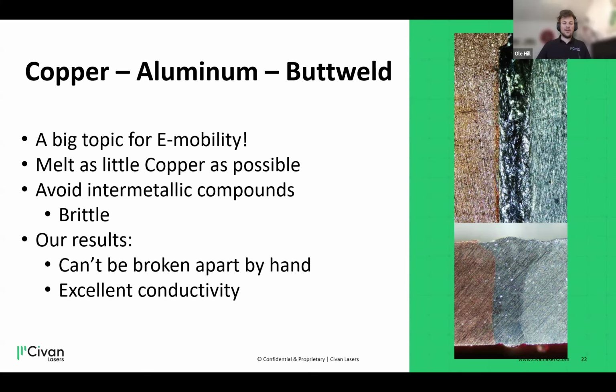So we had compared the conductivity of pure copper, of pure aluminum, and then the same width over our welding seam. And the conductivity resulted in basically, let's say, the weld didn't matter. We had the conductivity of copper and aluminum. If you add them up and divide them by 2, this was the conductivity that we achieved when measuring over the weld seam. So we are very excited to get this result.